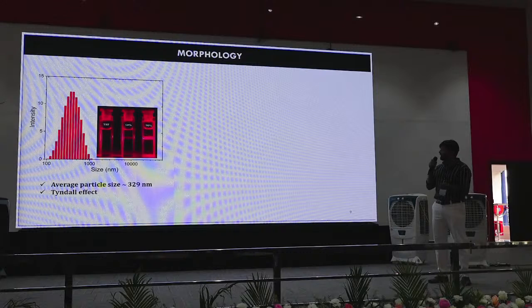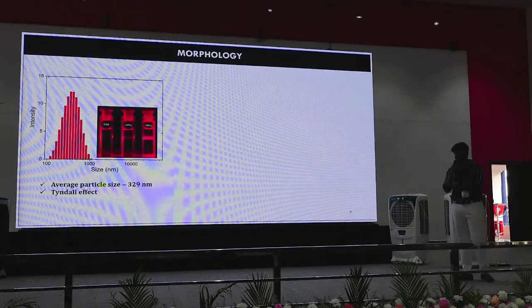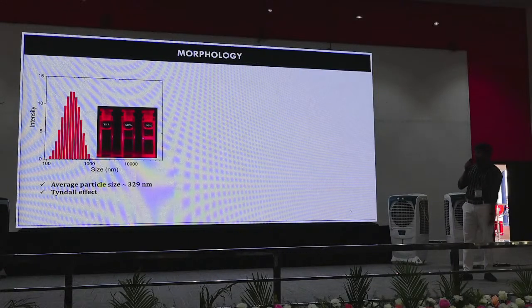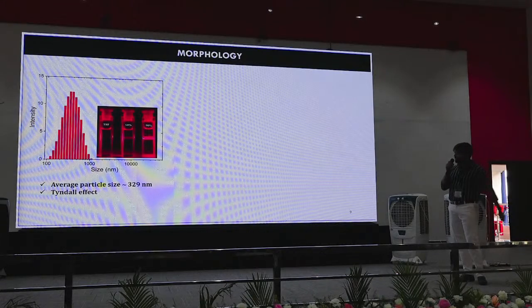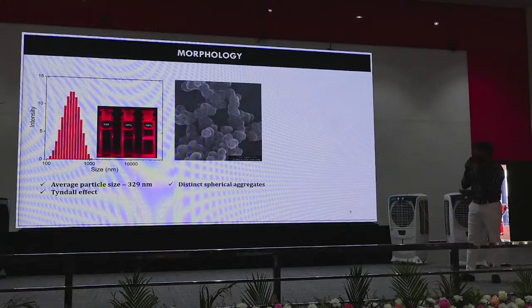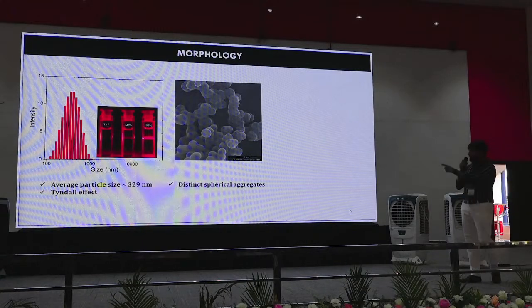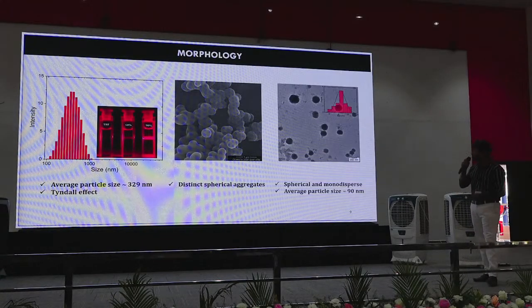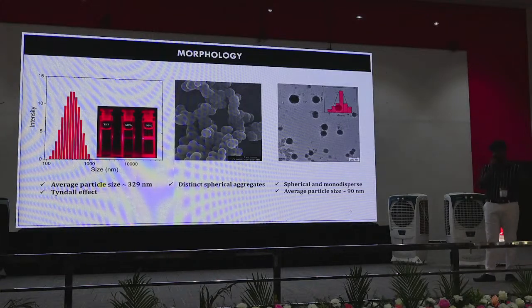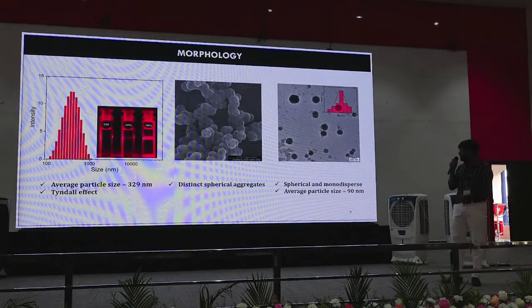And we have characterized the morphology of the aggregates. From solution state we have taken DLS, and we also did a simple Tyndall experiment. As you can see in the 90% aggregates, the scattering is more visible. And in the TEM measurements, they are characterized to be spherical aggregates, the average particle size is determined to be 90 nanometer, and it's also monodispersed.